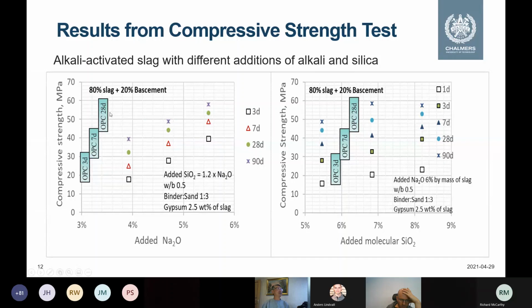Oh, this is 90 days. This is also in the range. So you can see this is sodium alkali content, and on the other side, silicon oxide content or silicate content. So you can see that if we have 6%, around 5% to 8%, this is 1 day, but 3 days it is already here, 7 days, 28 days, and 90 days. So if we increase the silicate content, we can increase the early strength. This is why we use both sodium content and silicate content to adjust our strength development.